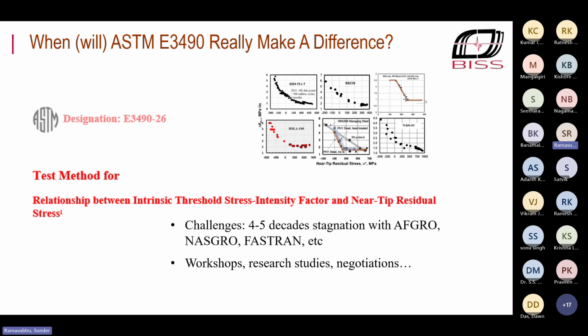It's an important point you make, and I mentioned that only in passing because AFGROW actually uses the corrected Willenborg model. Now, what happens is both the Willenborg and the Wheeler models use empirical constants to correct for load history effects. Those empirical constants are obtained from trial tests under spectrum loading under the same spectrum.